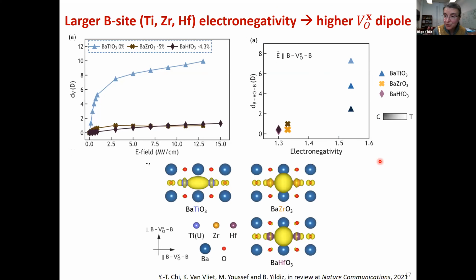And how about the chemistry effect? That is the electronegativity or electron sharing ability of the B site that is neighboring the polarizing electron. Now we are contrasting titanium with respect to zirconium and hafnium on the B site. And we can clearly see that the higher electronegativity system, titanate, can polarize much more strongly compared to the zirconate and hafnate. And if we plot the local dipole moment as a function of electronegativity, we can see that relation, the positive relation, very clearly. With the hafnate and zirconate, we have small polarization and much stronger with the titanate system.